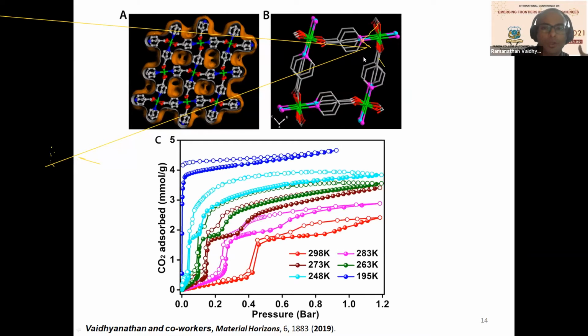Now, I do an adsorption with this MOF, okay? And I'm noticing at 195 Kelvin, it shows very good uptake of CO2. The pressure is on the x-axis and CO2 amount adsorbed on the y-axis. And this is the isotherm. Each curve represents measurement at a particular, fixed temperature. So at 195 Kelvin, I'm able to see a very good uptake of CO2. And as the temperature increases, the uptake falls, which is expected because adsorption is an exothermic process.